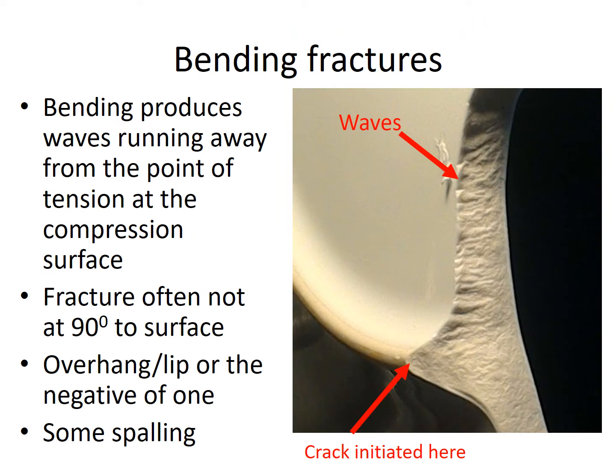Bending fractures also produce a lipped overhang at the point of the greatest compression, where the crack initiates, with a matching negative on the opposite fracture surface, like in this example. A very distinctive feature of bending fractures are ripples or waves running along the edge of the side of the fracture which was compressed. Bending also produces a ragged edge to the break and spalling. Textbooks on ceramic technology report other differences visible microscopically in fracture surfaces, which I have yet to consider in my study.